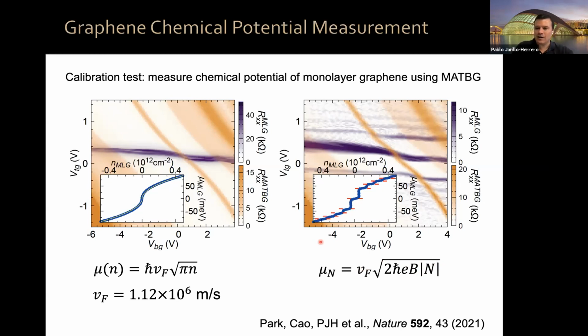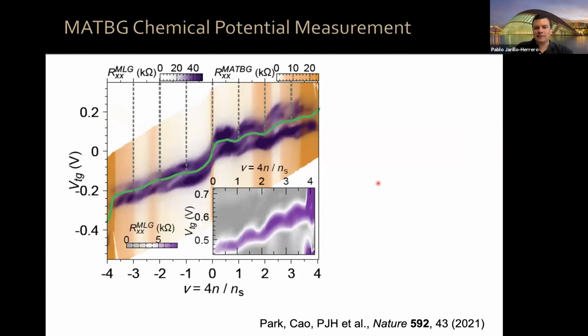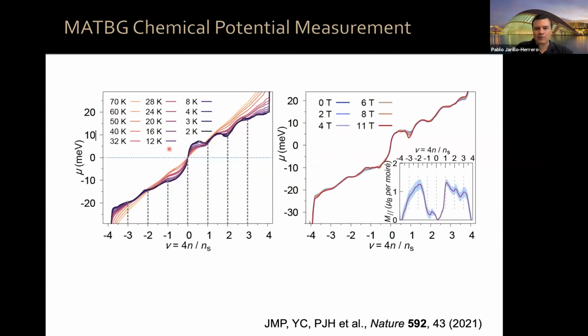Now let's do the opposite. Let's track the monolayer graphene in order to measure the chemical potential in the magic angle bilayer graphene. And this is what you can see here. This is the resistivity of the monolayer graphene, and you can see that there are these oscillations. So we can extract the chemical potential both as a function of temperature and also as a function of magnetic field. Very interestingly, through these chemical potential measurements and through Maxwell's relations, we can extract the entropy of the system, the magnetization of the system, which is shown here, etc.